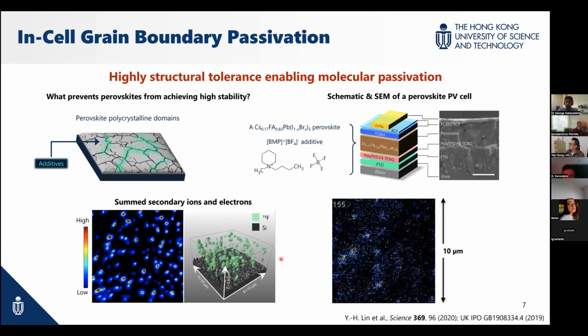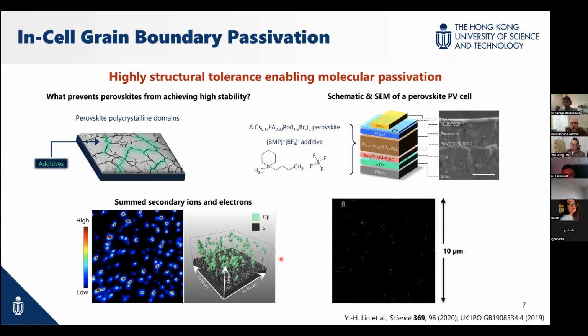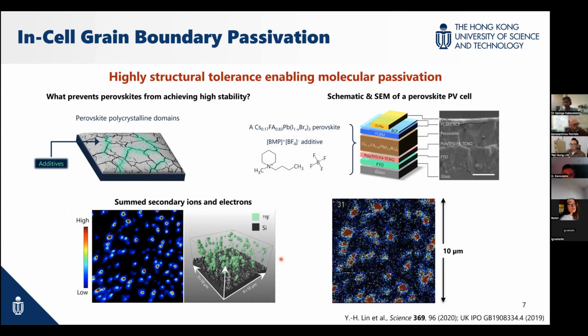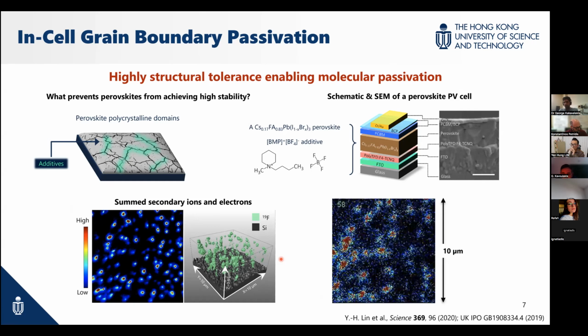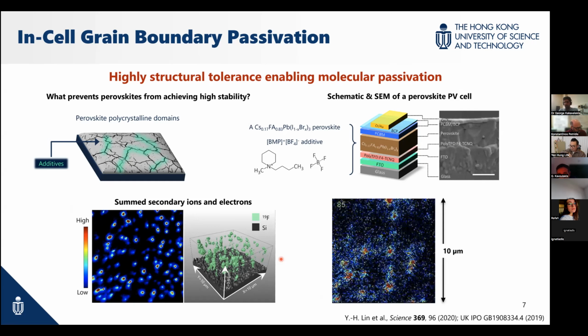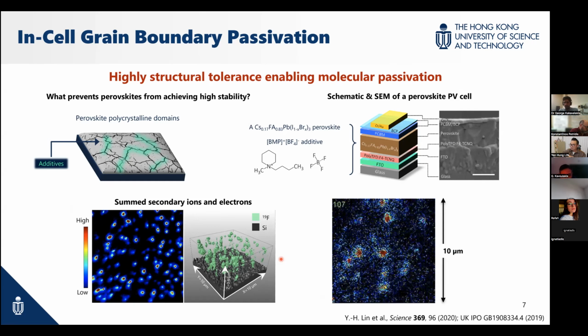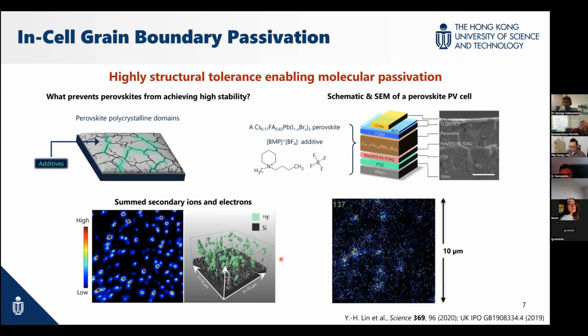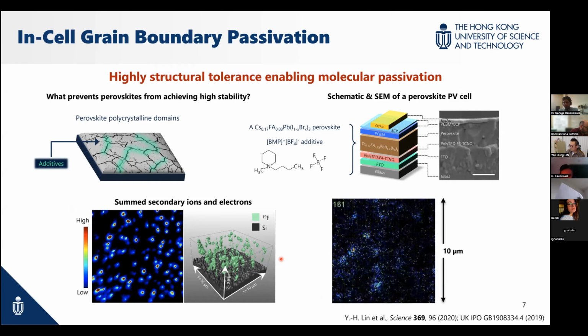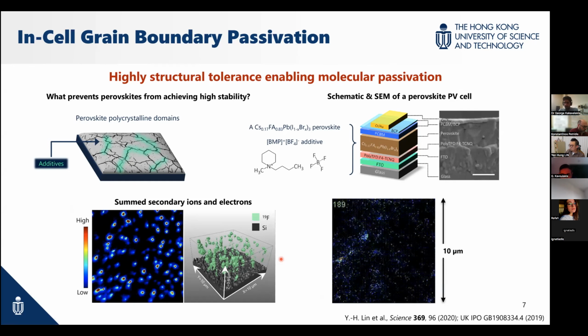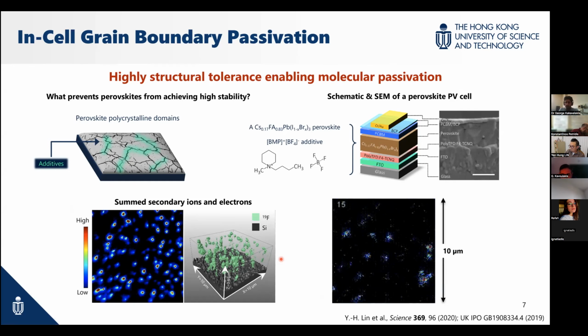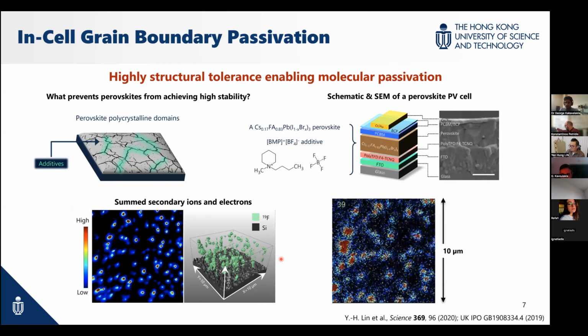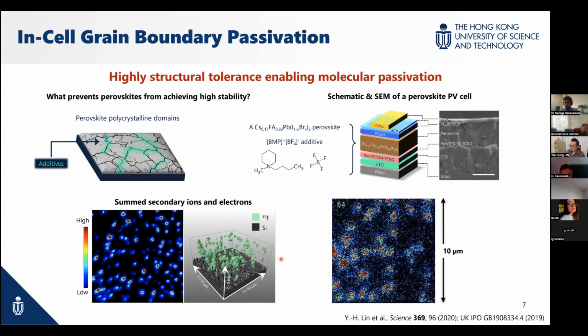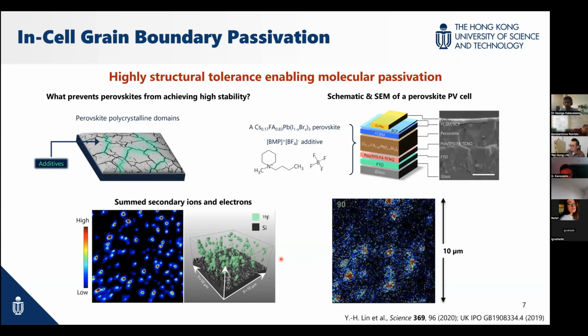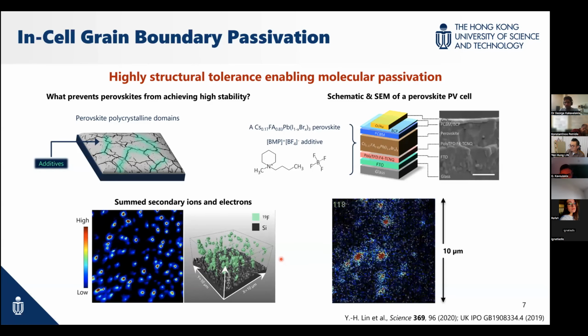Yes, indeed. I have seen many of these papers, where they're playing a bit with the composition between the JV result and the stability result. So we have to be very cautious about it. But what about my second part, about the passivation strategy? You mentioned you incorporated it in the bulk, but what about the surface? In this case, was there no surface passivation, or was it also passivated with this piperidinium molecule?